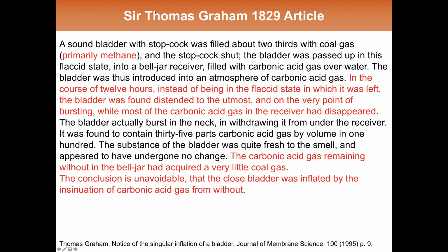Because what he found was that after about 12 hours, instead of this partially inflated balloon with methane in it, the bladder or the balloon was found to be distended to the utmost and at the very point of bursting. And most of the CO2 in the receiver had disappeared. And when he tried to take his balloon out of this device, it actually burst at the neck. Those of you who are involved in experimental research can feel his pain now, I'm sure.